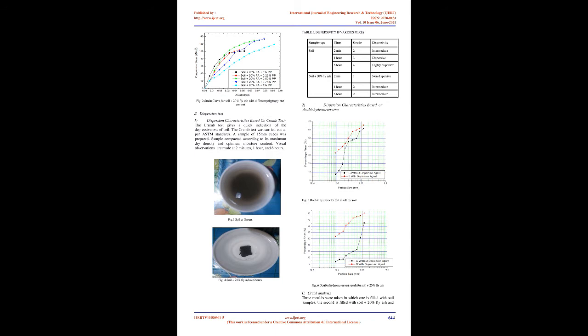Table 5. Dispersivity of various mixes. Sample type: soil, at 2 minutes, 1 hour, 6 hours. Grade 2, 3, 4. Dispersivity: intermediate, dispersive, highly dispersive. Soil plus 20% fly ash at 2 minutes: grade 1, non-dispersive. Fig. 2. Strain curve for soil plus 20% fly ash with different polypropylene content.